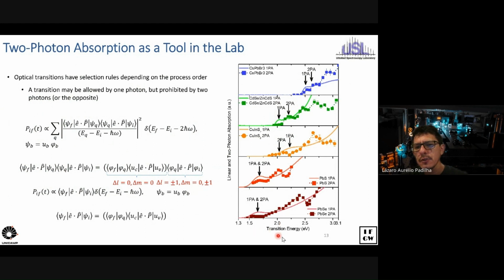Note that here I'm talking about transition energy. If you want to talk about the photon energy, of course, the energy of the photon for two-photon absorption is half of the energy shown here. For example, for this one, where it's 2.5 eV, each photon has 1.25 eV. For lead sulfide and lead selenide, the first one-photon and two-photon absorption are coincidental because of symmetry breaking, meaning they have transitions for one and two photons occurring at basically the same position. So this is a tool that helps us understand how these symmetries are held or not in these nanomaterials.